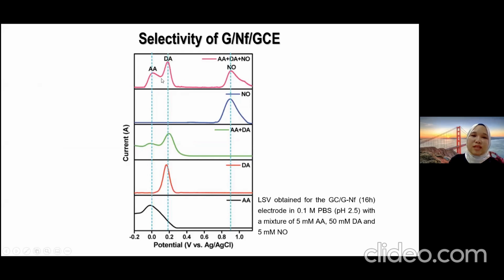So you can see that there is a very clear separation for those elements. So here represents the ascorbic acid and here is the dopamine. Whereas for the nitric oxide, it shows the high or significant peak for the current.